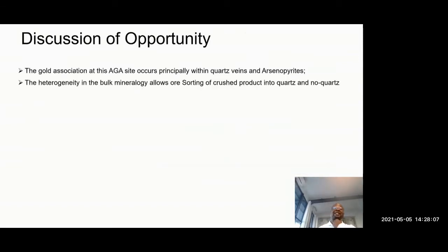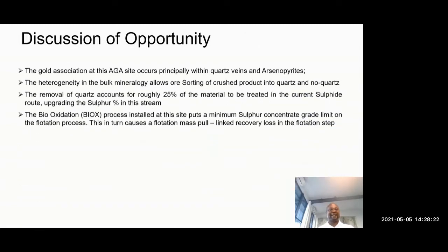Okay. So what is the discussion of the opportunity, as I just discussed? We are saying the gold association in this AGA site occurs principally within quartz veins and arsenopyrite. The heterogeneity in the bulk mineralogy allows ore sorting of crushed product into quartz and non-quartz. The removal of the quartz accounts for roughly 25% of the material to be treated in the current sulfide route, upgrading the sulfur % in this stream. Then the biooxidation process installed at this site puts a minimum sulfur concentrate grade limit on the flotation process. This in turn causes a flotation mass pull-related recovery loss in the flotation step.